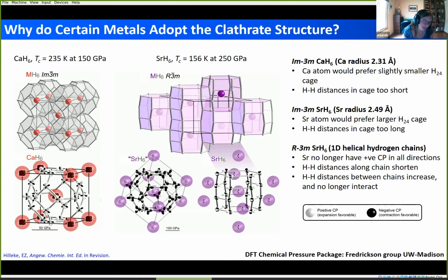If we calculate the chemical pressure maps, we see black around the calcium in this MH6 type structure, showing that the calcium is slightly too small for the hydrogen lattice. However, along the hydrogen-hydrogen bonds, we see positive chemical pressure, meaning the hydrogen lattice would like to expand. So you have this balance of chemical pressures keeping the structure together, where the calcium is a bit too small, but the hydrogens cannot expand further.